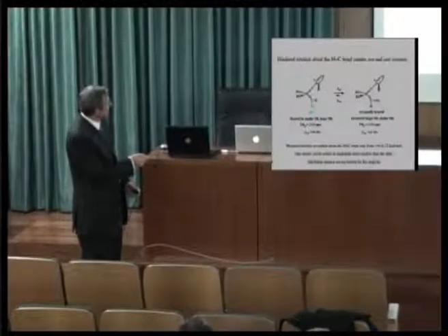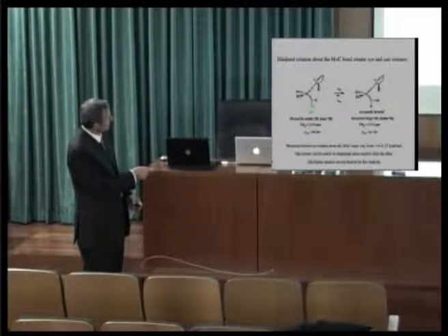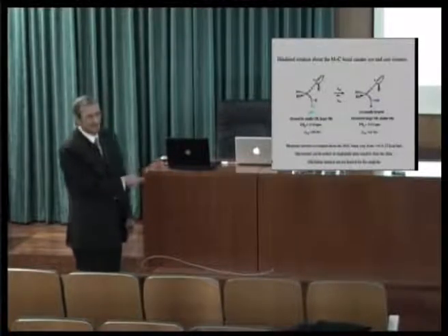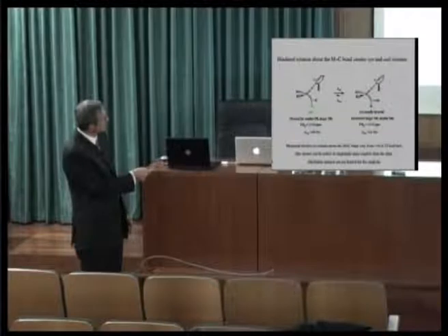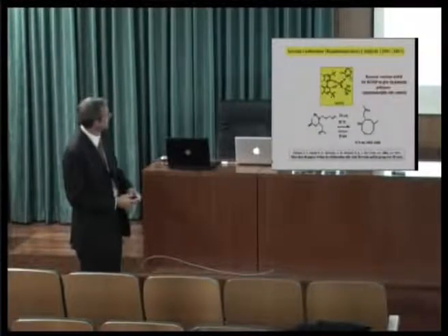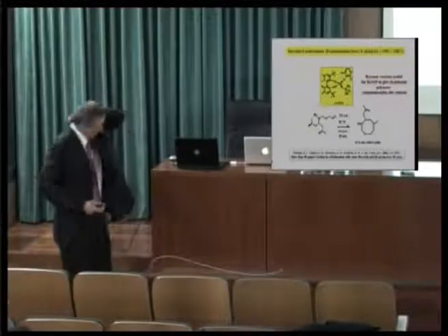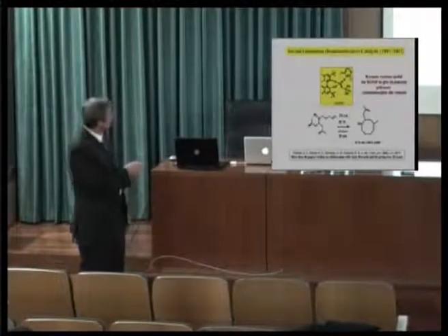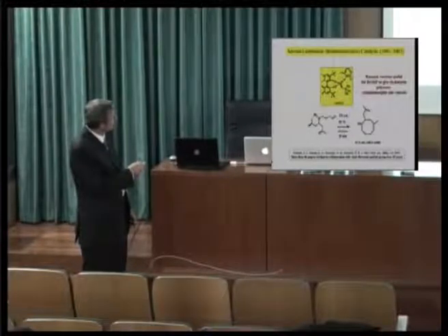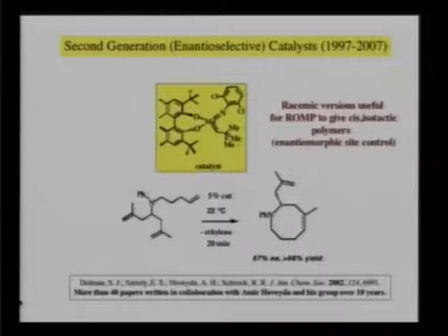We know that the strength of the bond, or the barrier to rotation, is roughly 20 kcals. So these are rotating readily, and these at the top are not rotating rapidly at all. The second generation catalysts were enantioselective. So you just join the oxygens together with some enantiomerically pure ligand, biphenolate, binaphthalate. You notice the amido group is the most effective one, is now this dichlorophenylimido group. And then you can make enantiomerically pure products with this chiral enantiomerically pure catalyst.